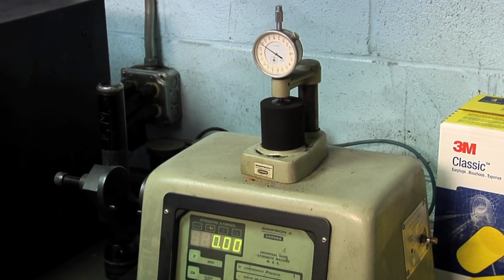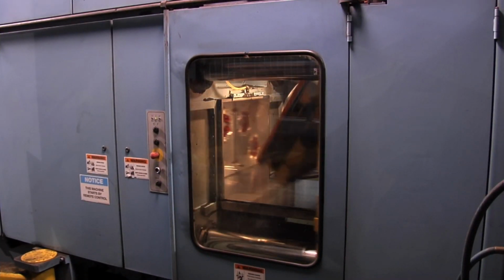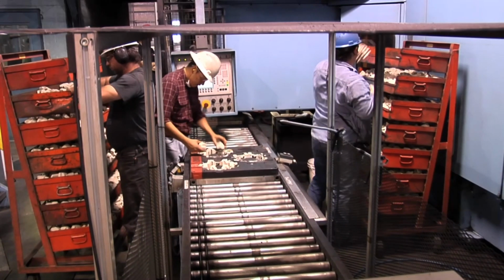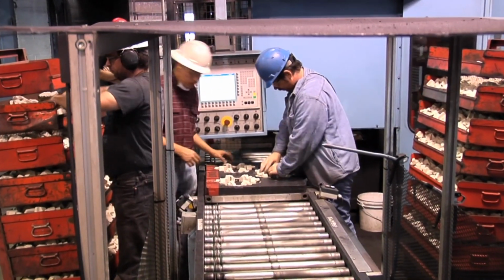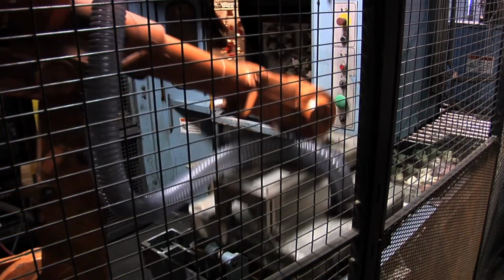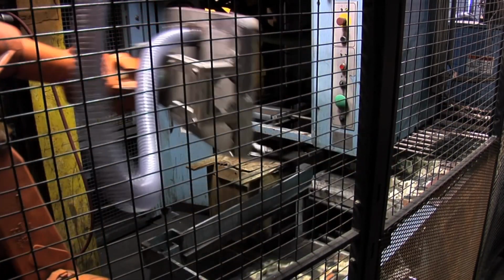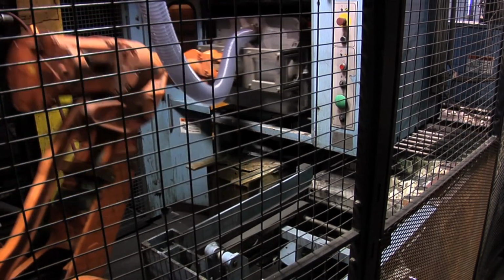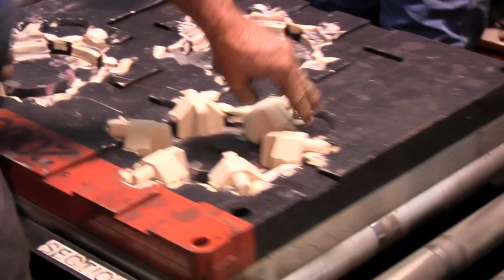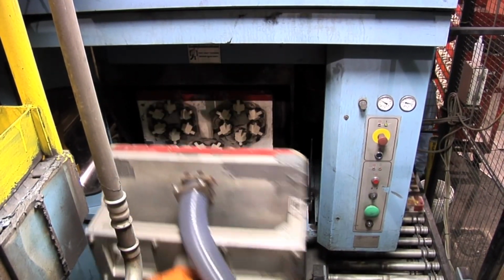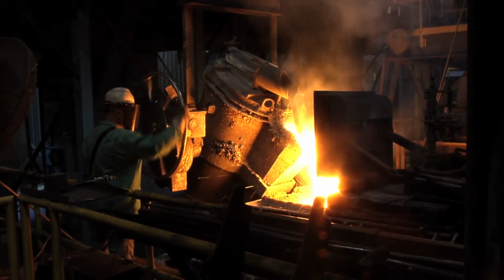Once all the correct properties have been verified, the sand is transported to the molding machine area. Here, high-speed automatic molding machines compress the sand mixture into highly defined mold blocks, containing the impressions of each casting's final shape and form. Cores are set with the aid and precision of EBAA's sophisticated and automated robot core setter, installed in 2006, which increases the efficiency and speed with which EBAA can generate high-quality castings. The compressed sand mold blocks automatically form an assembly pouring line as they exit the molding machine every 10 to 12 seconds, and then are transported by conveyor to the pouring area.